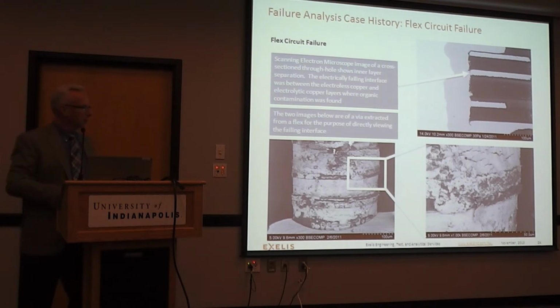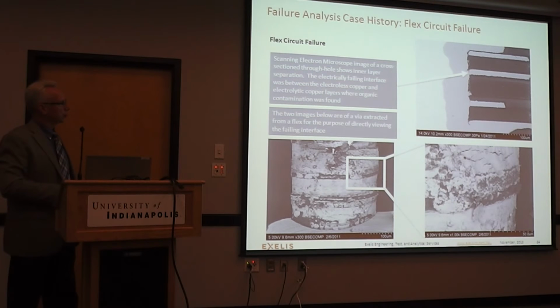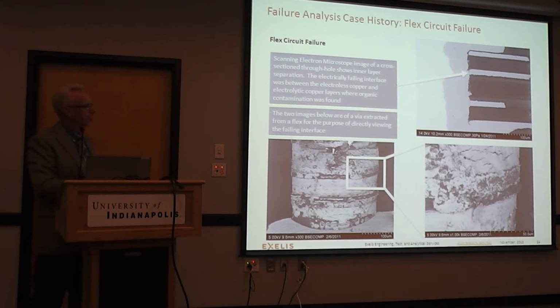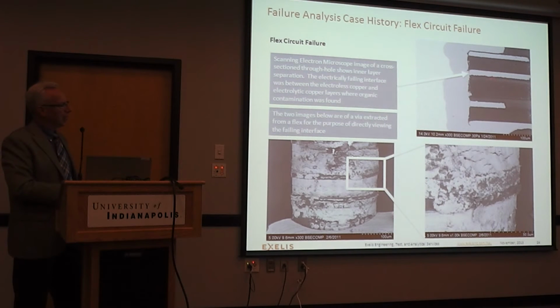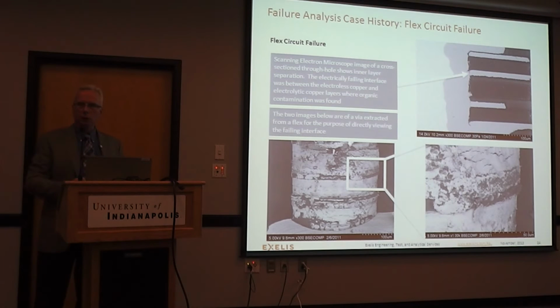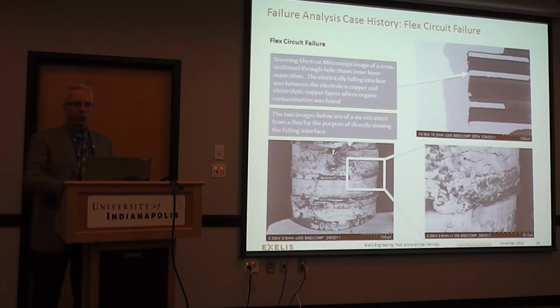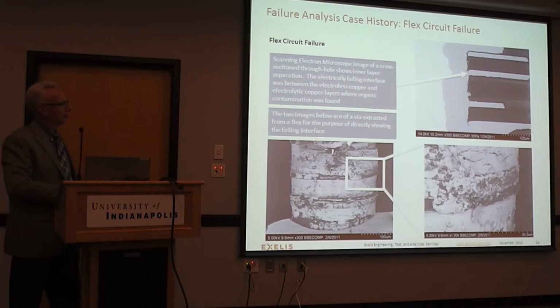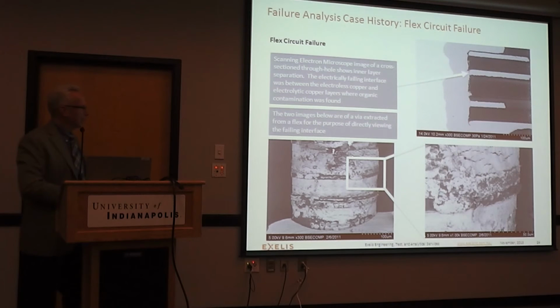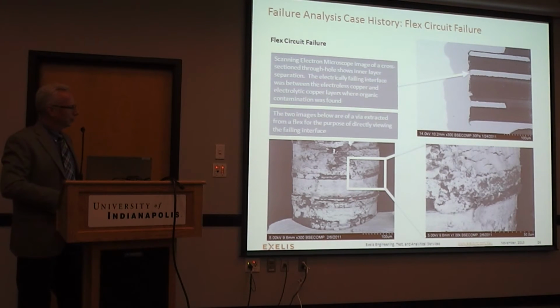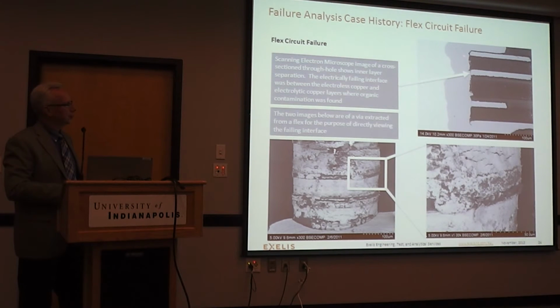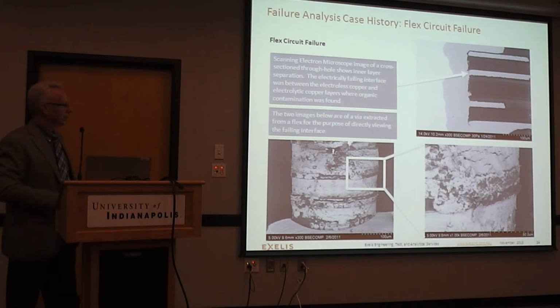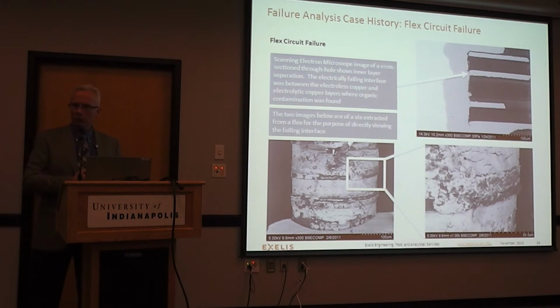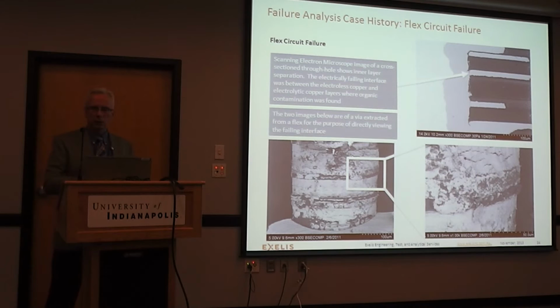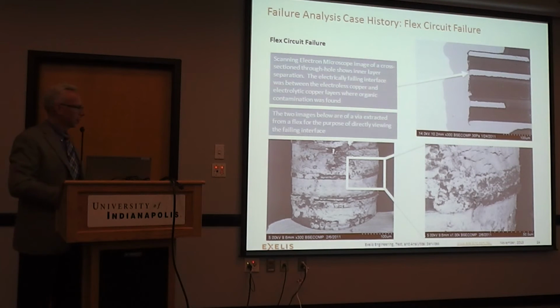Well, that's where we really had to earn our money. We performed an extraction. We cross-sectioned that plated through hole up to about the 50% point, and then we extracted it out of the circuit. So behind these traces would be kind of a mixture of Kapton and different polymeric materials. And we essentially pried that half circle out of that circuit and then analyzed the surface. So these features here line up with the T-joint, okay? And so you're seeing this dark material is actually an organic material on the surface at the T-joint interface. It ought not be there. That ought to be a good metallurgical bond, so that you have good electrical continuity.